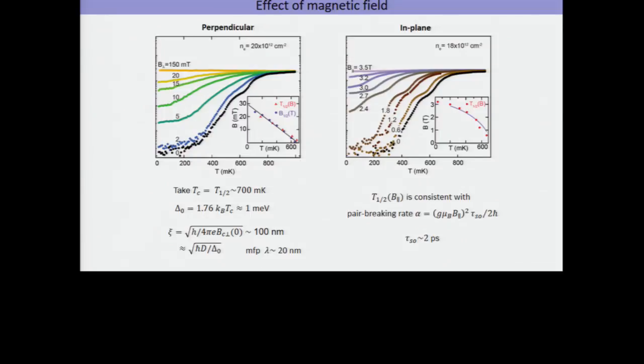It's something we don't understand, which I skipped over, which is that the edge conduction in WTe2, in both our devices and I think in the MIT devices, eventually at low enough temperature, freezes out. It becomes gapped. So below 1 Kelvin in this device, there's no edge conduction left. So all we're doing is measuring the bulk conductivity here.